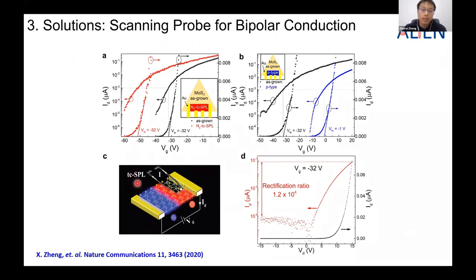We have created a p-n junction on a monolayer MoS2 transistor, and if you look at the IV curve, we can observe a very significant current rectification. And if you look at the rectification ratio, the ratio is as large as 10^4. This is the largest ratio in a monolayer MoS2 transistor diode.